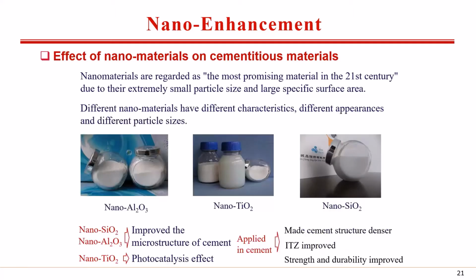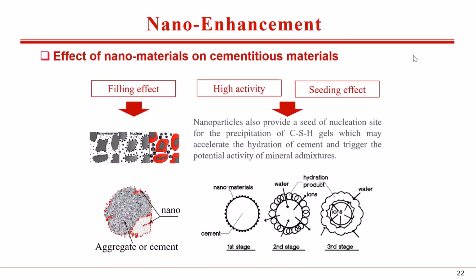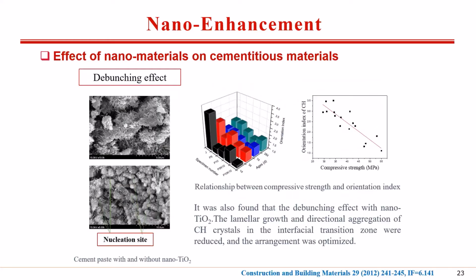From this slide, we can know different kinds and different properties of nanomaterials could cause different effects on cement and concrete. However, the mechanism still focuses on the filling effect, high activity, and the seeding effect of nanomaterials. We need to conduct further research. We found compressive strength of cement paste is linearly related to the orientation index of calcium hydroxide. Thus, we propose a new mechanism of nanomaterials, the debunching effect. Some detailed results will be published in the near future.